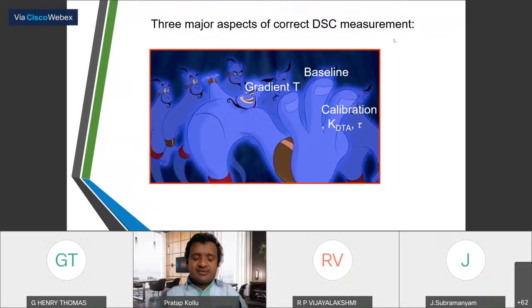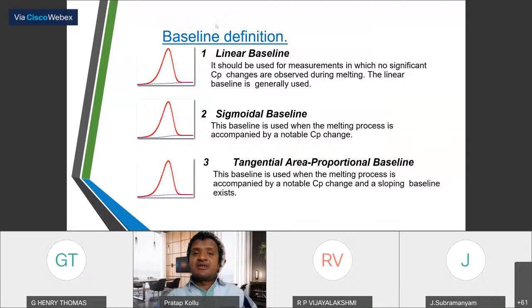When you measure DSC, there are three components that should be monitored: gradient, baseline, and calibration. Why? Because when you measure any material using DSC, you will get data, and for that data, corrections are always required. So how do you correct the baseline? Linear baseline, sigmoidal baseline, and tangential area proportional baseline.